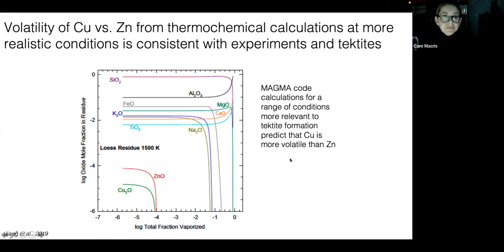So one last figure. Here I'm showing a figure from Jiang et al. 2019, where they used MAGMA code to do thermochemical calculations at conditions that are relevant to tektite formation. They used loess as a starting composition, and they made this plot showing the composition of a residual melt after being heated to 1500 Kelvin as a function of the total fraction vaporized. This is on a log scale. What we see here, or the takeaway, is that copper is lost before zinc and is therefore more volatile at tektite forming conditions, which is contrary to those predictions based on the half condensation temperatures.